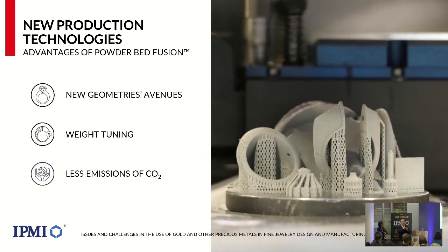For marketing positioning, because you have a ring that the designer is making. The weight is 15 grams, but then you need that ring at 13 grams without changing the apparent volume. And how to do it? Then you empty the inside. But you do not make it super hollow. You just make it a little hollow. And this is something that you can do only with additive manufacturing.